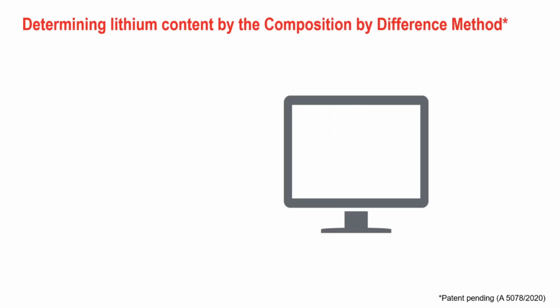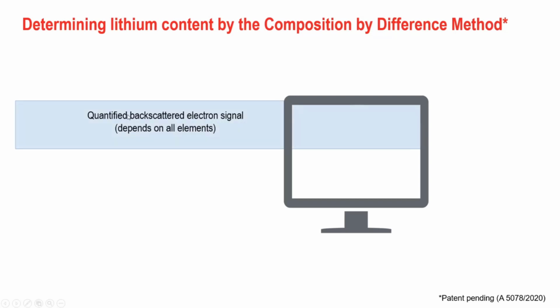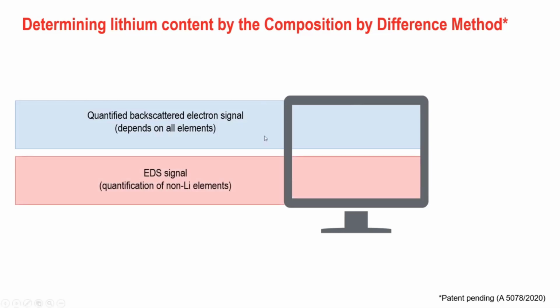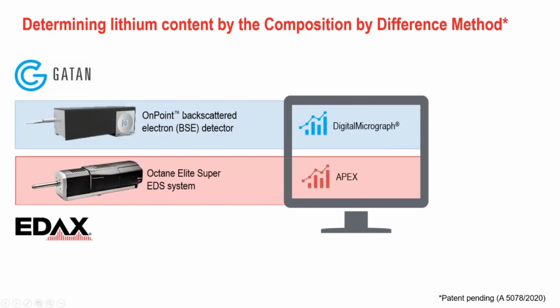And a new tool has been developed. It's a combined technique where we are looking at a backscattered electron signal that we quantify. So we look at the backscatter coefficient of the entire area, and then we also look at the EDS signal, so we quantify whatever composition we have. To do that, here we use the Gatan OnPoint detector, which is a very sensitive low kV backscatter detector, and the Octane Elite Super. That's for the EDS analysis.